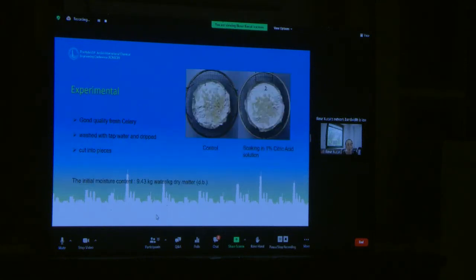First of all, fresh celery was obtained from the local market in Istanbul. The fresh celery was washed with tap water and cut into pieces. Pieces were about 6 millimeters, and the initial moisture content was determined as 0.43 kilogram water per kilogram dry matter. The celery samples were divided into two parts. One is the control part, and the other was soaked in an acid solution as pre-treatment.